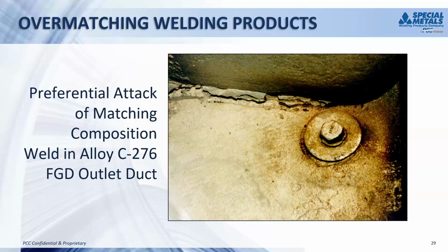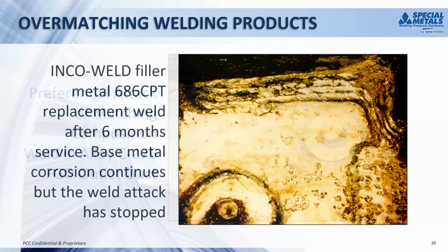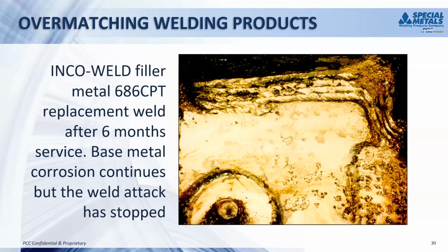There's certainly attack of the base metal as well. The next slide shows, in an attempt to repair that, the weld was replaced with filler metal 686 CPT. And after 6 months, that weld is in good shape. We're not seeing any corrosion there, but the base metal is continuing to corrode.